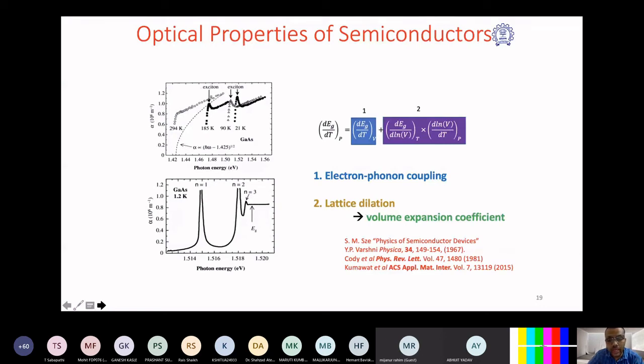But that was an empirical relation. In actual sense, the semiconductor band gap changes because of two reasons. One is electron-phonon coupling, and another is lattice dilation. Each and everything expands or contracts with respect to temperature; it's just that the numbers are different. If you give heat to a plastic, it expands more, whereas a solid does not expand as much, but a solid also expands. Glass has its own expansion coefficient. So semiconducting materials also have lattice expansion with respect to temperature, and that gives rise to lattice dilation, because expansion means the lattice size is changing. So we look into that aspect. There are two aspects because of which the band gap changes.